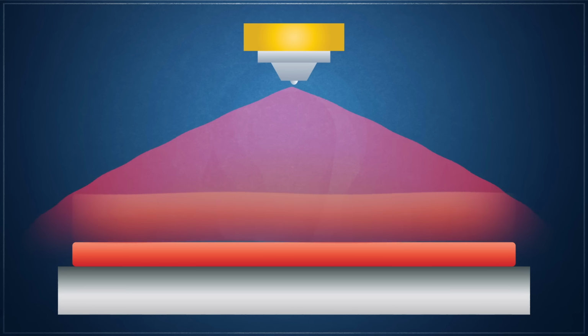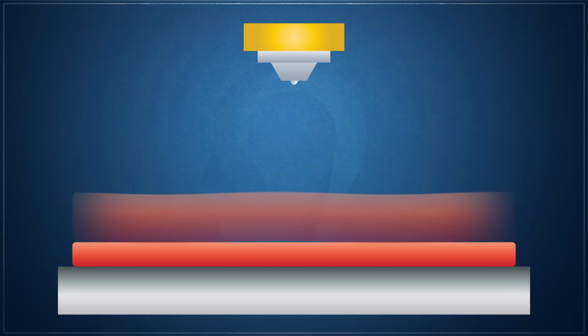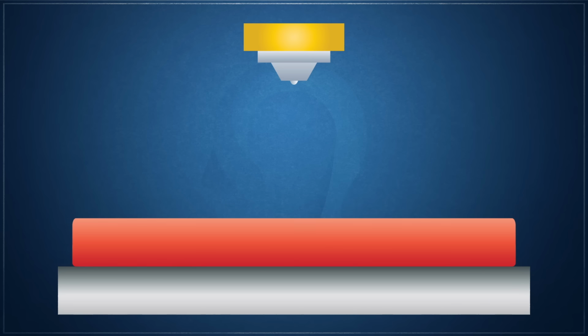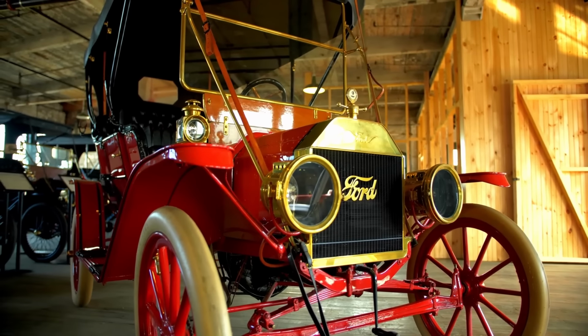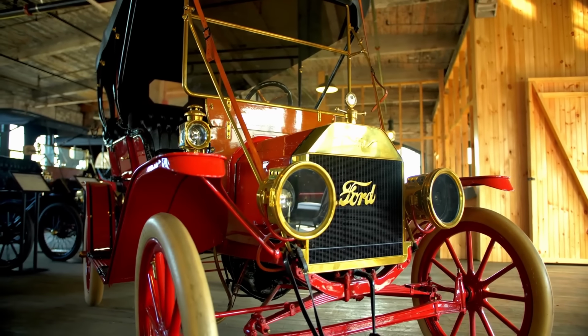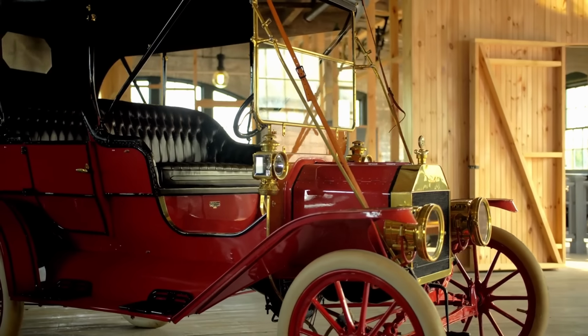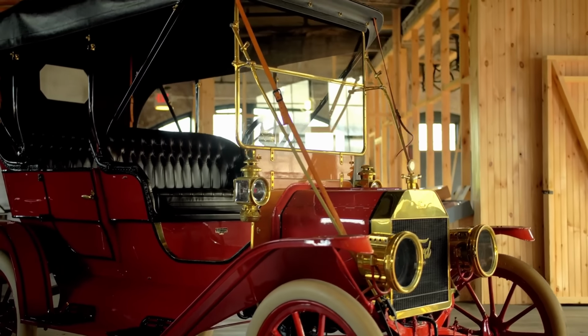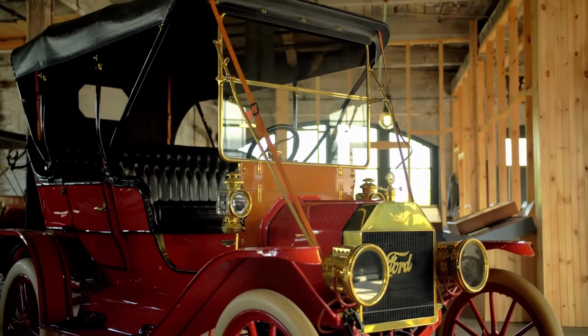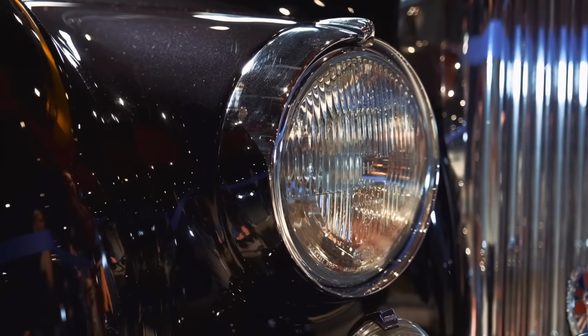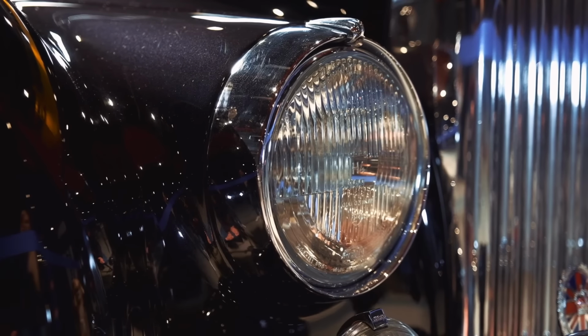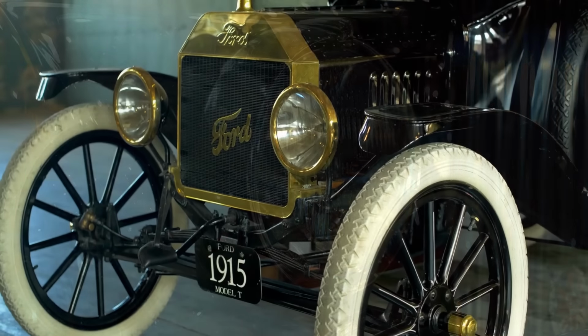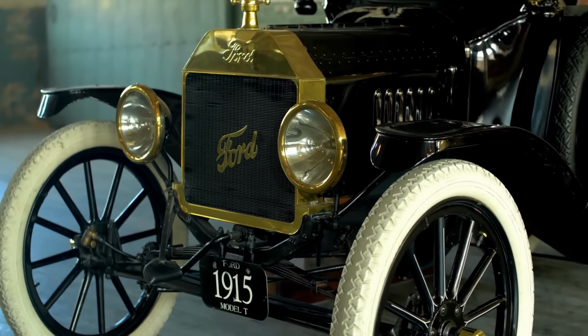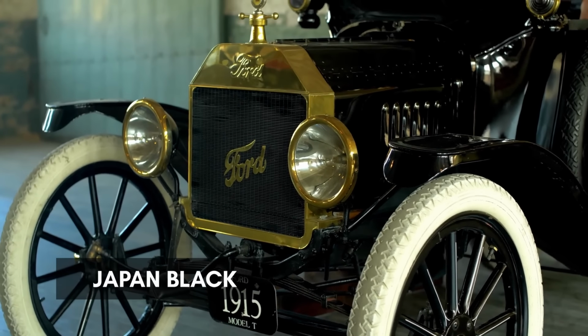When additional coats are applied, the solvent mix melts the surface of the previous coat, allowing the fresh coat to bond with it. Nitrocellulose lacquers have the advantage of being extremely fast-drying, and they produced a tougher, more scratch-resistant finish. They also take pigments and dyes very well, and can be sanded and polished to a mirror finish. Offering far more aesthetic options, it quickly replaced the previously fastest drying lacquer option based on asphalt, called Japan Black.